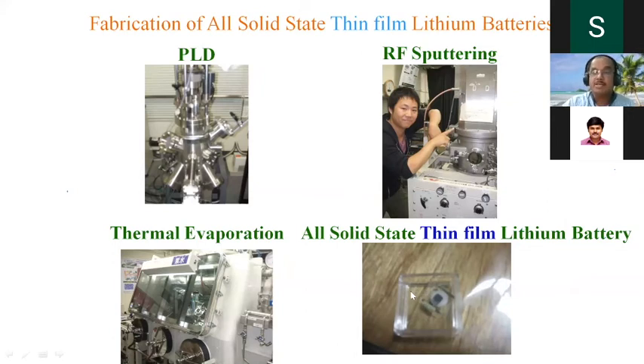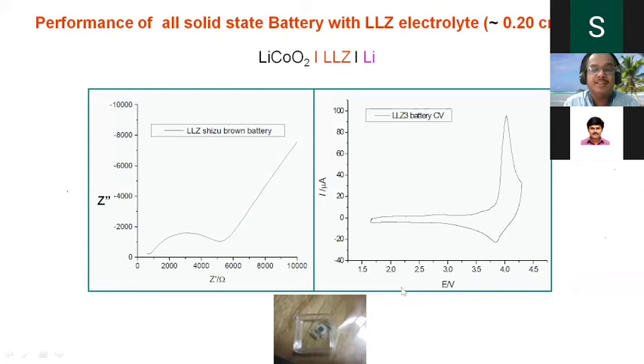If you ask me, the result was very, very, very poor. Believe it or not, with the lithium cobalt oxide, LLZ and metallic lithium, I was unable to glow even an LED. It's in microamps, not even milliamps. So we understood. People thought that once they find a suitable material, they can immediately fabricate the all solid state battery, because the technology has been demonstrated for lithium ion. But they are having difficulty scaling up. That's why they couldn't. So our success story is, we thought we would succeed, but we failed in the first attempt in 2010 at Toyota.